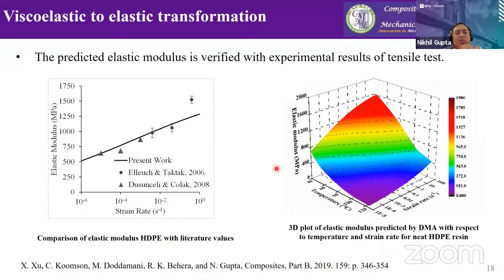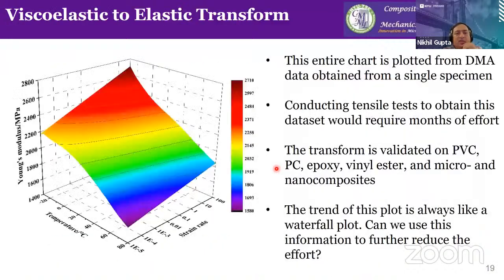So what you can imagine we have achieved here is very simple. The entire chart of elastic modulus with respect to temperature and strain rate is captured from just one single experiment in DMA. So we did the temperature and frequency sweep on that one specimen. And once we applied our scheme of conversion, then this entire chart of E prime, or the storage modulus, is now converted to Young's modulus with respect to temperature and strain rate.